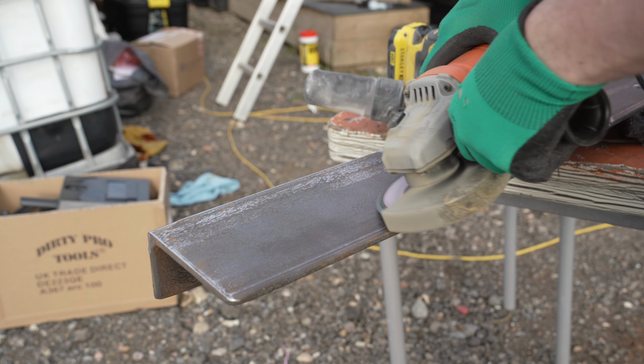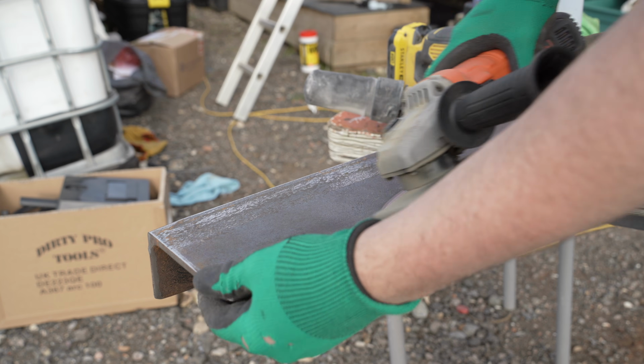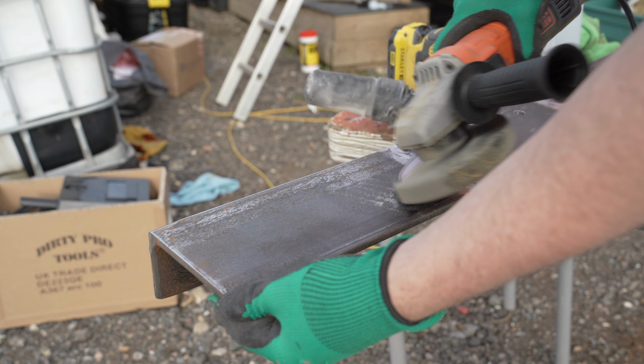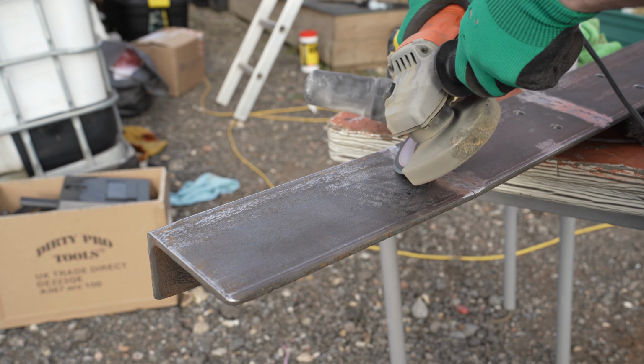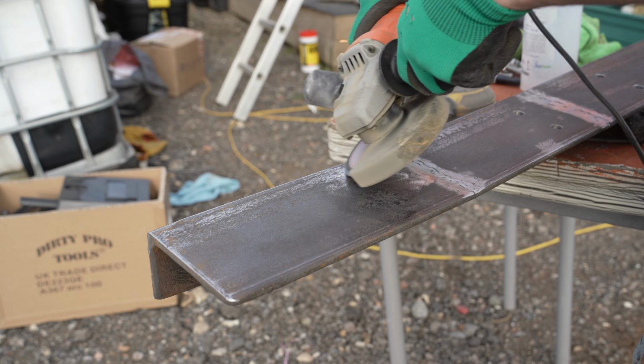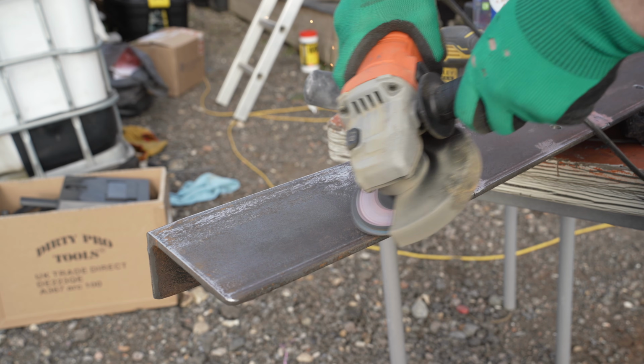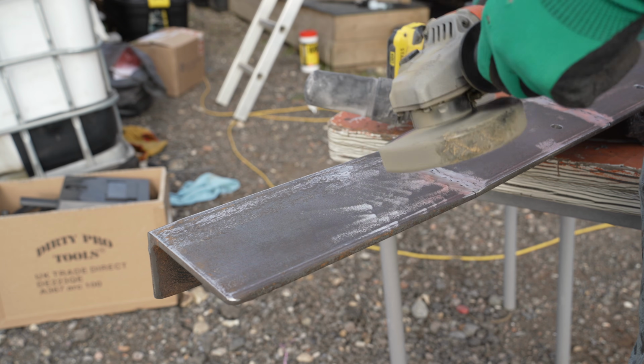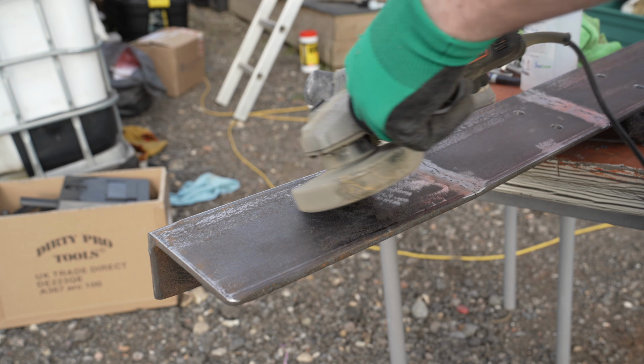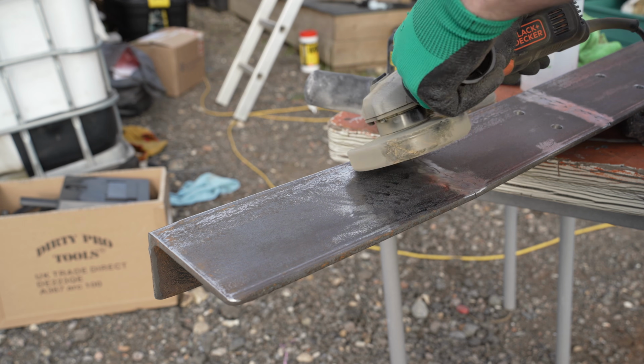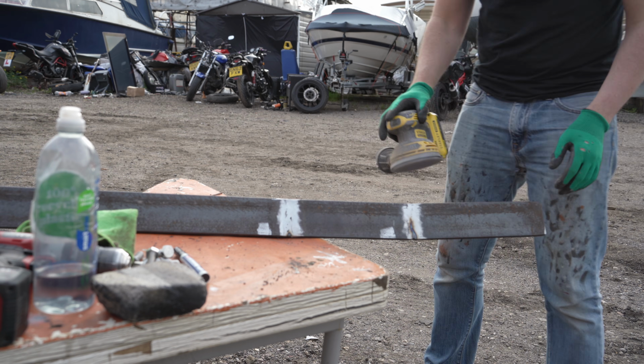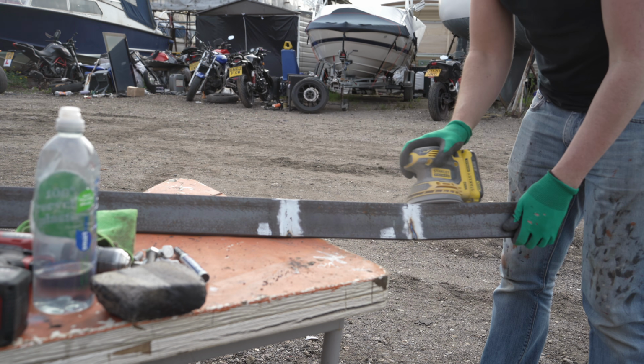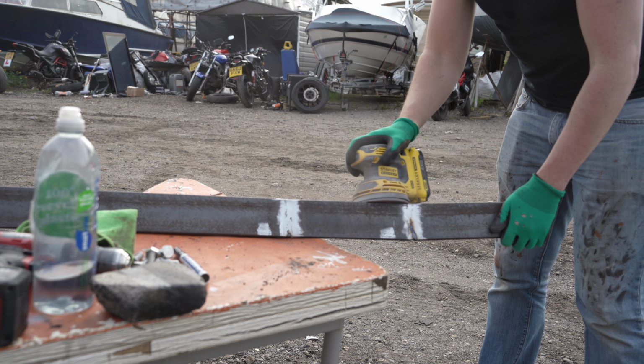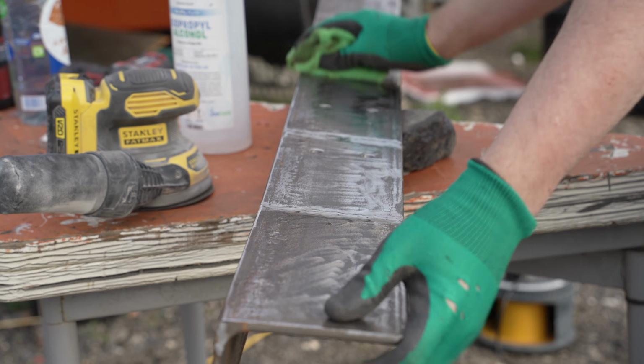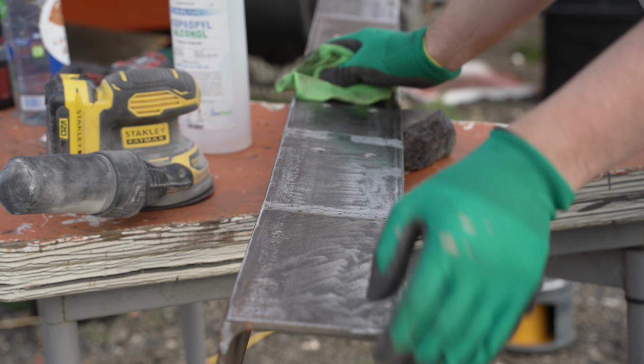The large piece of steel isn't ready to be plonked onto the transom just yet, as there's been some very light corrosion, and even on delivery, it wasn't a bright, lightened steel. I want to give the epoxy and the sealant the best chance of staying put long term. So a flap wheel on the grinder brightens up most of the vertical rear face of the bracket, and then I went over with the sander for good measure. Finally, to make sure that we haven't left behind any dust, oils or other assorted grot, I gave it a wipe down with some acetone solvent.